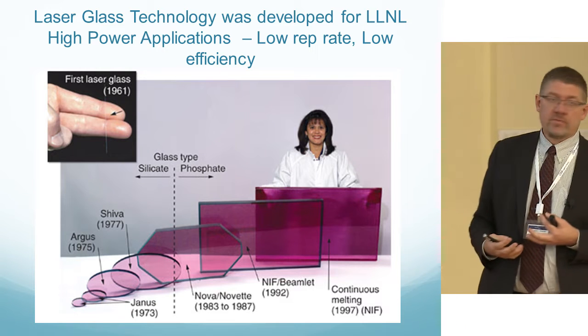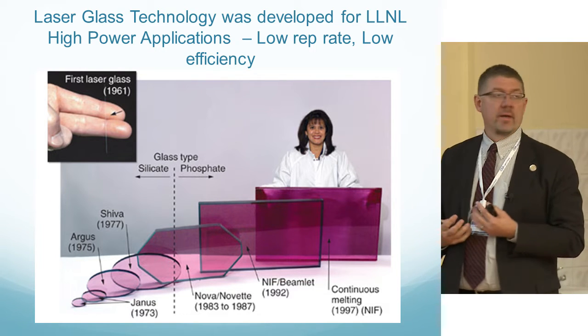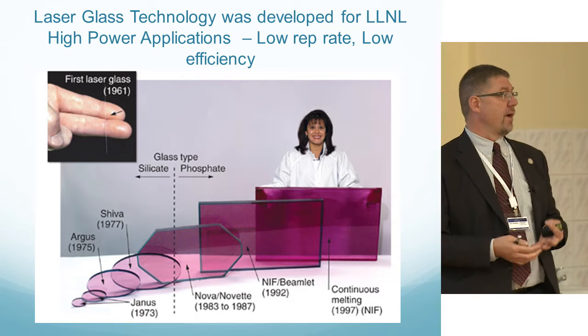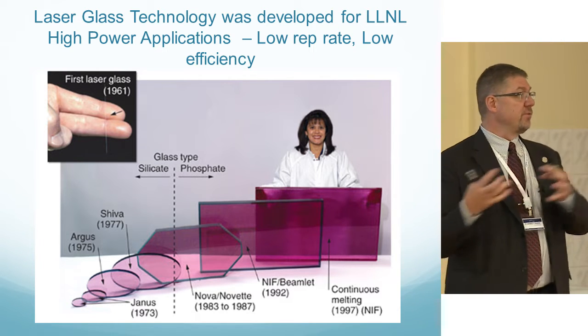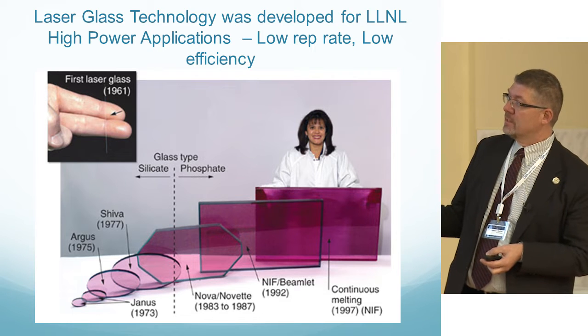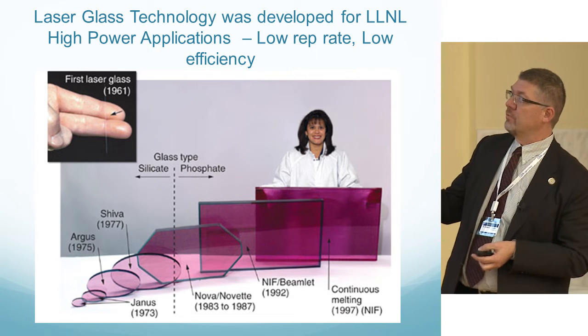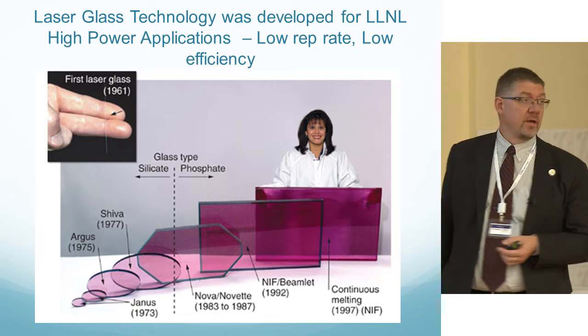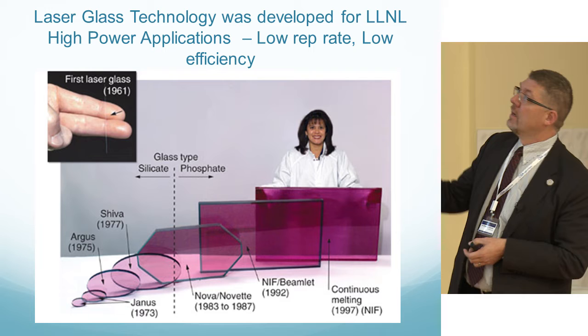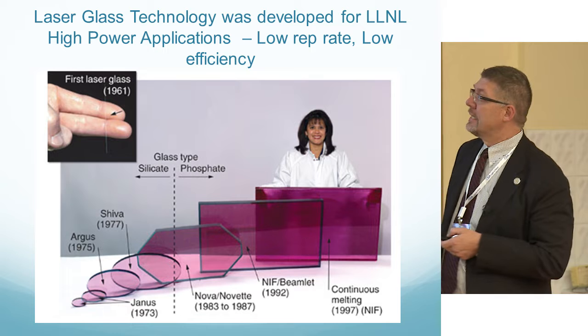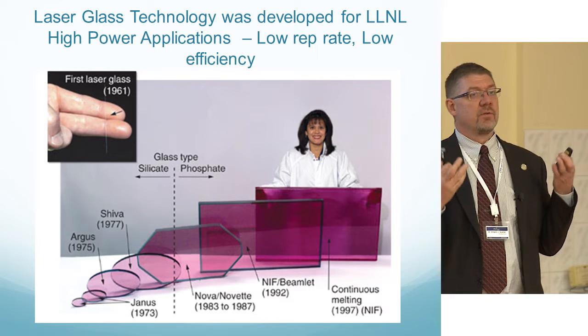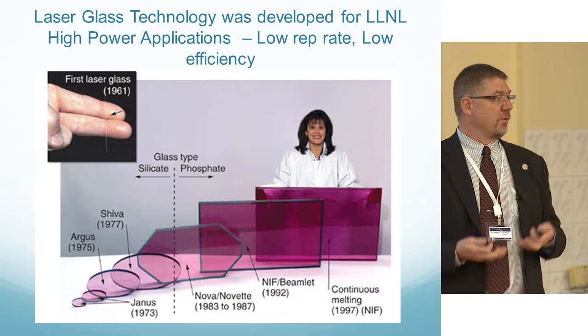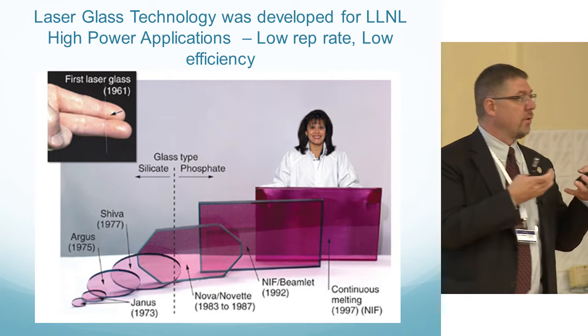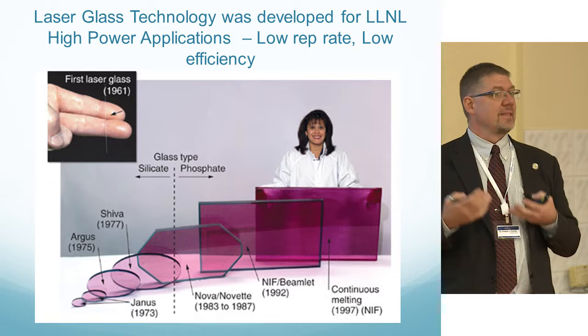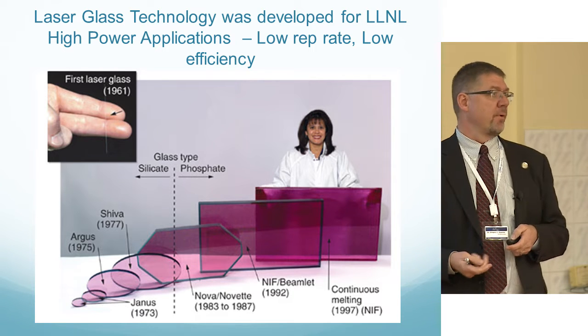In the 1970s, many of the federal labs went to trying to develop glass lasers for inertial confinement fusion. They thought that they could grow bigger pieces than they could get with a single crystal, so they went from 4 inches in diameter up to a continuous melt that you see here that's an extremely large cross-section piece of glass. Here's the first glass laser up here in the top left photograph from 1961. The only problem with glass, as everybody knows, thermal conductivity is horrific. So if you're going to run anything at a very high rep rate, or there's going to be a lot of thermal load, the glass is going to start to break down or limit the operation of the laser.